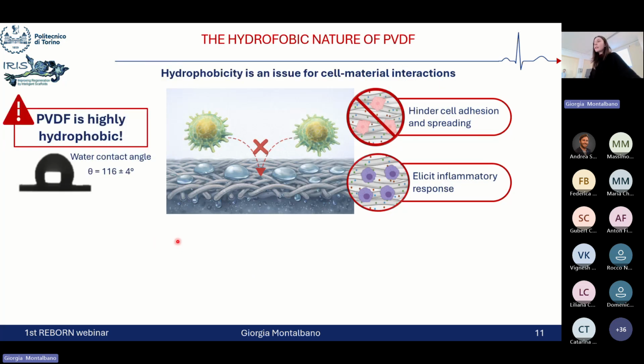So despite all the great advantages that are represented by this material and the positive aspects that we have listed before, for sure, one of the main limitations of PVDF is its intrinsic high hydrophobicity. And as we know, hydrophobicity can be a real issue for an effective cell-material interaction, where the hydrophobicity of the surface can hinder cell adhesion and spreading, while inducing a local inflammatory response.